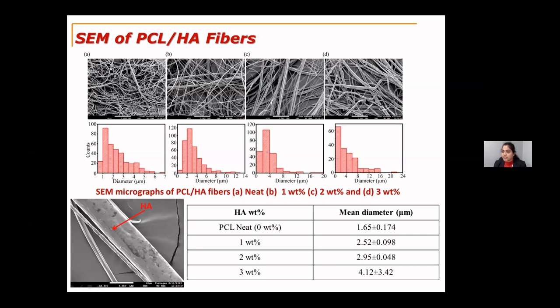When the filler percentage increases, the hydroxyapatite nanoparticles agglomerate, and these particles come together and form clusters. As you can see here, the fibers bulge out at the center because of the agglomeration of these particles, and the fibers with the higher weight percentages are mostly disoriented and non-uniform. We observed very thick and very thin fibers for this.